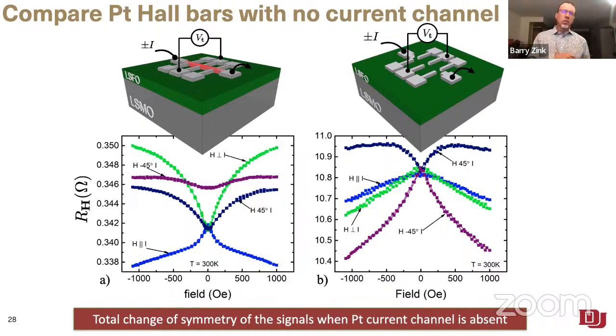We're still measuring the transverse voltage with the same sort of voltage tap, right? So that's what's shown on the right here. The thing to note is that the raw signal voltages are actually much larger. That's partly because we no longer have a direct current path in the platinum across our experiment, so we're not shunting the thing out anymore. That's why the signals are larger. But the really notable thing is that the symmetry of the signals has totally changed.